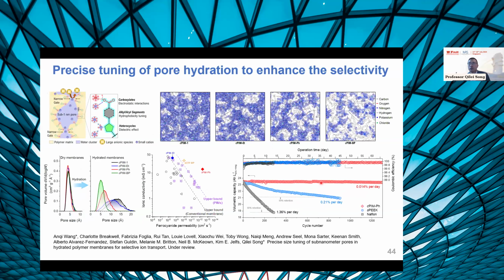Based on this work, we also developed some other carboxylated PIMs. So we were able to tune the hydrophobicity of the side chain. We got really good performance. This new generation of carboxylated PIMs was resistant to swelling. This is very important because traditional membranes, if you expose them to water electrolyte, swell. When they swell, they lose the selectivity because the pore size distribution becomes much broader. That means the redox species will also diffuse through the membrane. With this new generation of membranes, we can see that they were able to retain the pore size distribution, so they can retain the high selectivity.